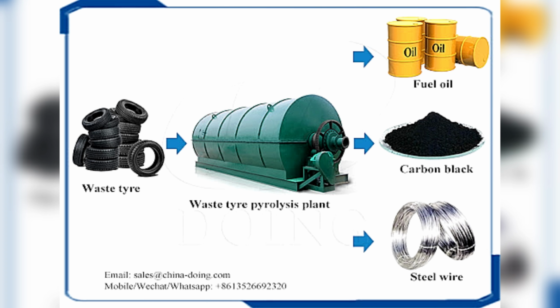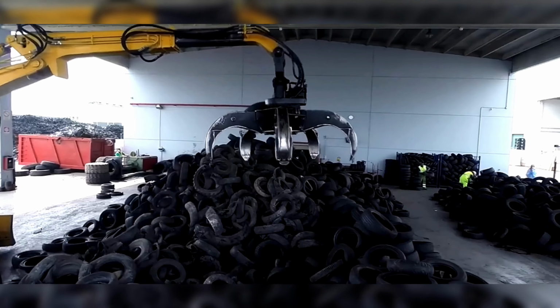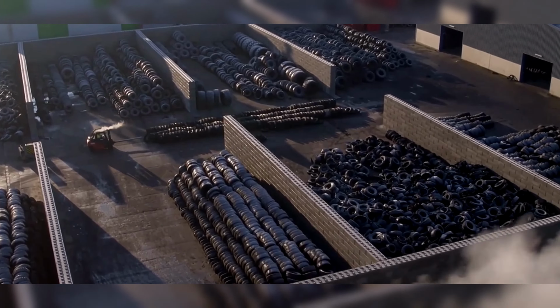Another widely used commercial rubber recycling method is pyrolysis, a thermal process that breaks down rubber into valuable byproducts like oil, gas, and carbon black. Unlike combustion, which burns rubber and releases harmful emissions, pyrolysis occurs in an oxygen-free environment, preventing complete oxidation and instead causing the long-chain polymers in rubber to break into smaller molecules. This happens inside a sealed reactor at temperatures between 400 Celsius and 600 Celsius, where the rubber decomposes into pyrolysis oil, syngas, and char. The oil can be refined into fuel or used as a feedstock for chemical production.